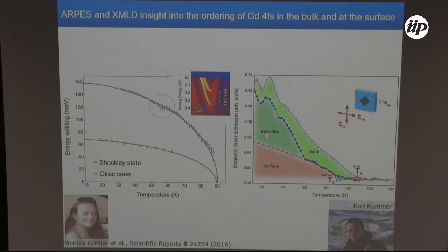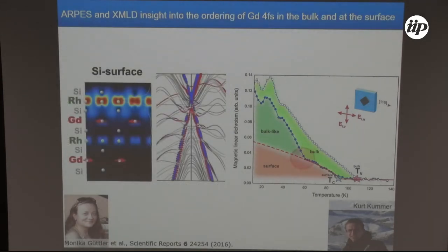This can be interpreted as these two subsystems — the surface and the bulk — becoming coupled to each other through exchange coupling along the c direction. Some states must mediate this coupling — exactly what kind of states is still unknown. We are discussing the possibility that the cone feature, which may be part of the donut and is strongly coupled to other bulk bands, might participate in this coupling action.